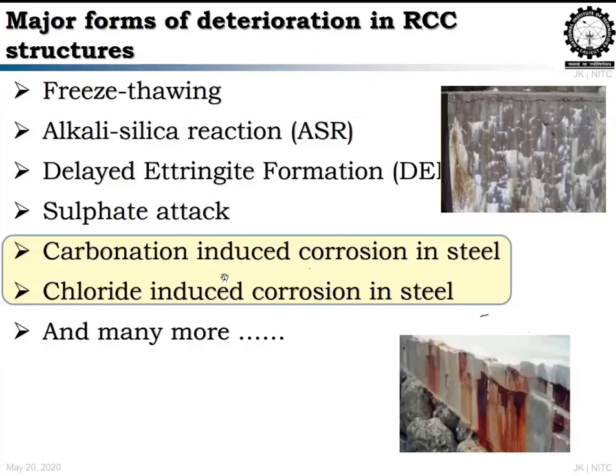But freeze-thaw in India is very rare, very close to the Himalayas. We have a few problems, but it's not a major problem in India. And we have very good aggregates where we don't have alkali-based aggregates, so we don't expect much alkali silica reaction. Delayed ettringite formation is a very rare case to happen; most of the time our climate condition is not so favorable for it. Sulfate attack, obviously we don't have, because of the quality cements that most companies are manufacturing, and also our soil conditions and water, whatever we are using, don't have much sulfate.